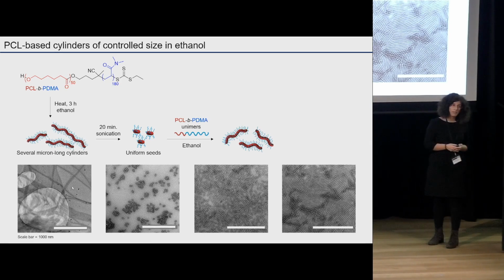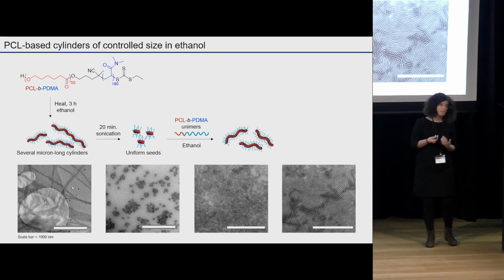To achieve control of the size, we sonicate the cylinders to form what we call seeds. The reason we call them seeds is that we can then grow from them by adding a sequential amount of polymers in a controlled fashion. And so you can get any size that you want. However, as you can see here, we do this process in ethanol.